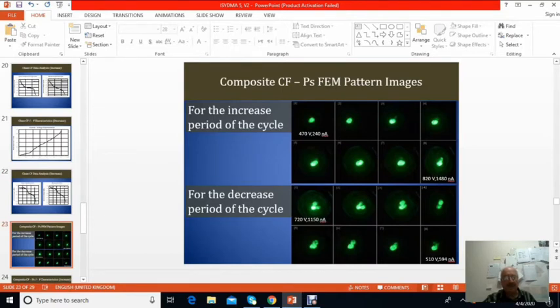Composite carbon fiber polystyrene coated field emission microscope pattern. You can see this is 470 volts, 240 nanoamperes. And here we end up with 820 volts, 1480 nanoamperes. Quite an improvement. And this is for the decrease. You can see this is the same image, and this is going down: 510 volts for 584 nanoamperes.